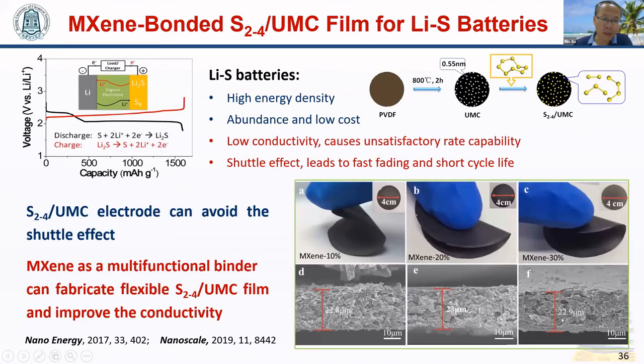These methods can also be extended to lithium sulfur batteries. Previously, we prepared the S2-4/UMC electrode, which can avoid the shuttle effect. To meet the requirements of flexible devices, we combined the MXene binder with the S2-4/UMC electrode. By simple vacuum filtration of the mixture of these materials with MXenes, we can also get a freestanding flexible film.